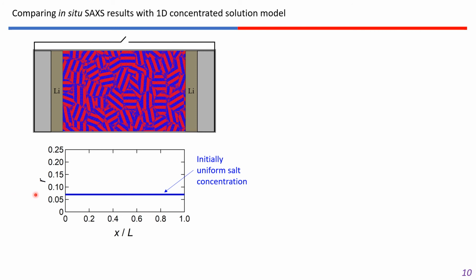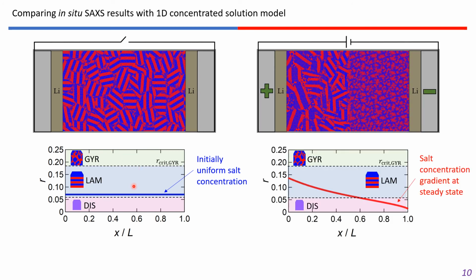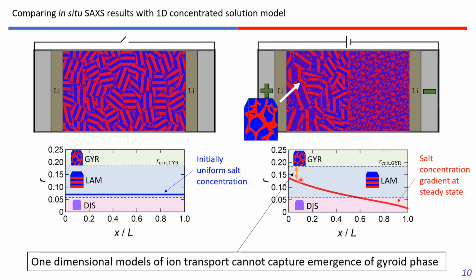Initially, our cell is of uniform salt concentration and in the lamellar phase, shown here. The salt concentration is near the lamellar to disordered boundary, but is relatively far from the lamellar to gyroid phase boundary shown here. At steady state, after 8.3 hours of polarization, we have some pockets of gyroid phase forming. But if we look at the salt concentration gradient at steady state, which we just confirmed experimentally, we see that the maximum salt concentration is relatively far from what we'd expect to be required to form the gyroid phase. And so it's clear that our one-dimensional models of ion transport cannot capture emergence of the gyroid phase, and there must be another explanation.